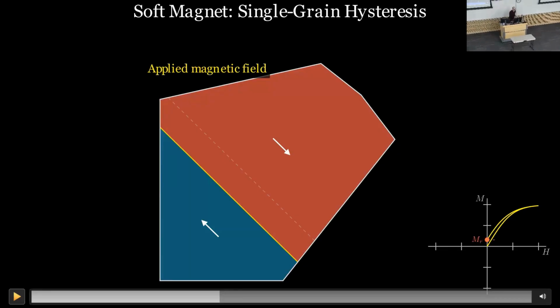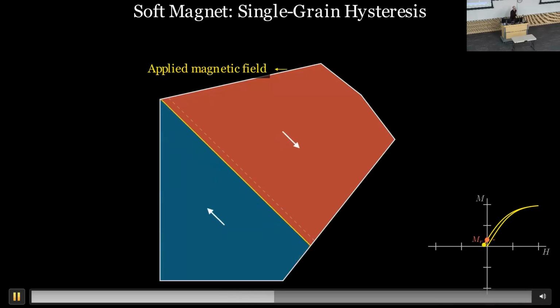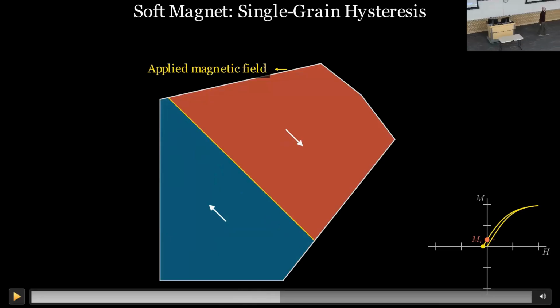Another question that's very important for us is how hard is it to demagnetize the material? Like, how hard do I have to push to get the yellow line to go back to where it started from? Usually you have to apply a little bit of a field in the opposite direction. See that? Just a little bit of field, and we demagnetize the material. That's not good, right? If you want a permanent magnet, you don't want it to be easy to demagnetize. Okay, so we want a really large x-intercept. This is the x-intercept, how hard it is to demagnetize. And we want a really large y-intercept, which is how much magnetization we were able to achieve.